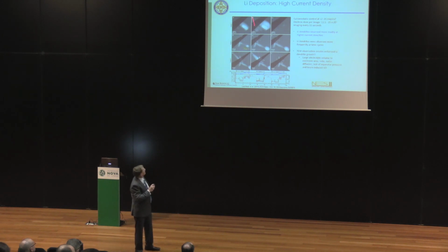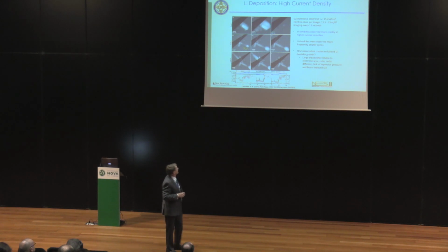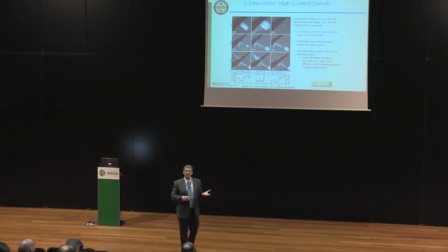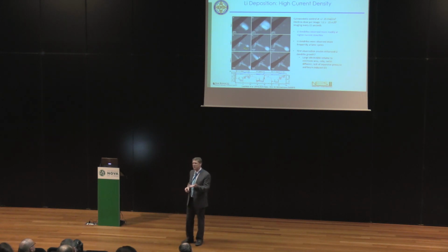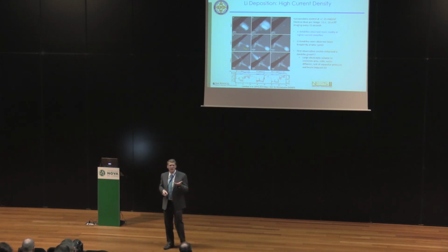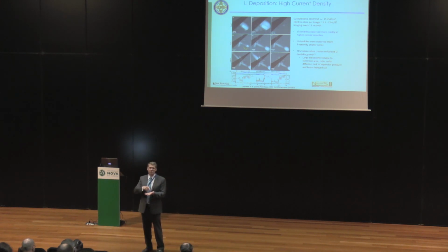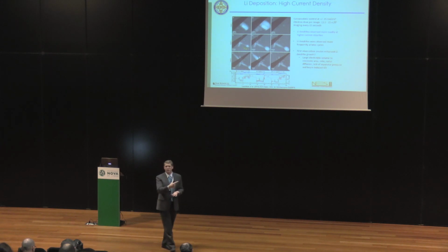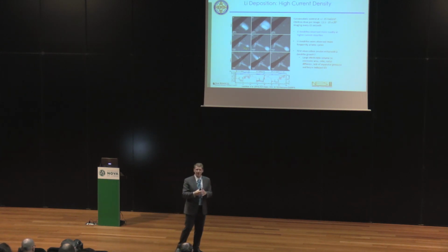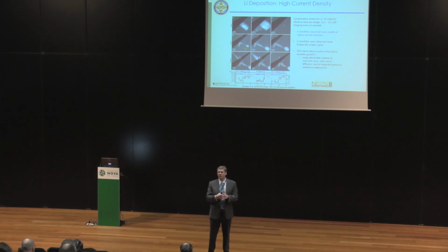All right, so what do you see? Well, now you get very large dendrites forming. So this is clearly unstable. And this is a situation which you wouldn't want to actually use in your energy storage system. So this is one of those fundamental limits of lithium in a lithium-based battery. If you increase your deposition potential, the instabilities in the surface cause dendrites to grow. And these dendrites can possibly pierce through your barrier layer between your anode and cathode, and that would then cause a short, which in turn volatilizes your electrolyte, and everything goes up in a rapid thermal process.